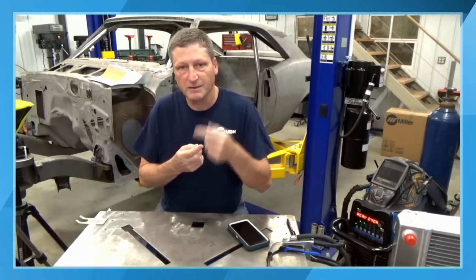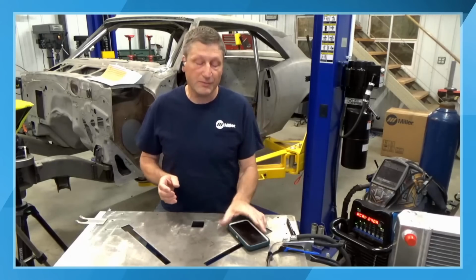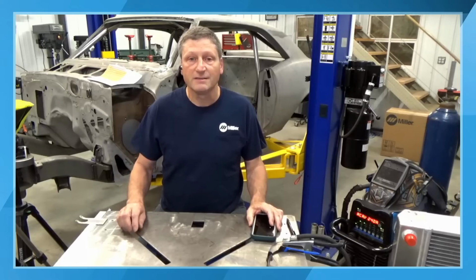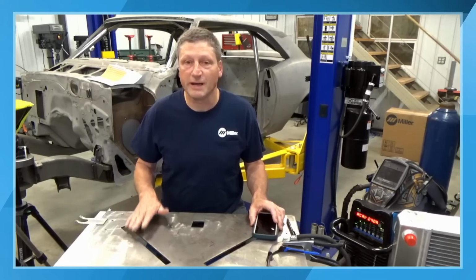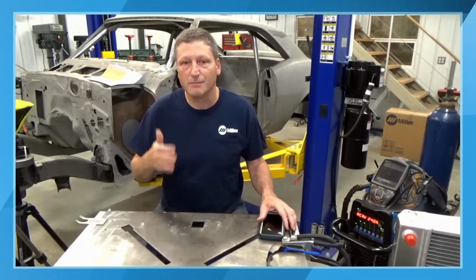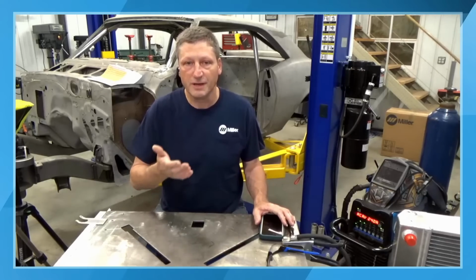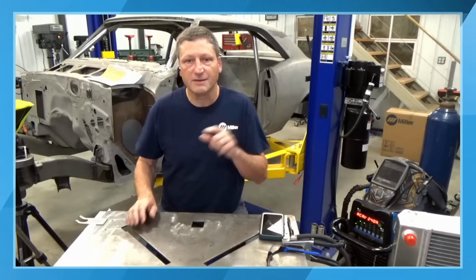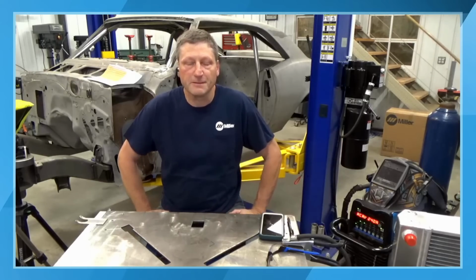If you're going down to a C rating, then C means you have to take into account some additional welding parameters, and again, we're going to talk about base metal dilution. If you can dilute enough of the base metal in with the filler metal, then a C rating would make it somewhat acceptable. If you're going with something that is C rated, I would recommend calling the manufacturer of the filler metal and telling them your application, and they could give you a better estimate of whether you will have enough base metal dilution in the filler metal to give it that property. I hope that makes sense.